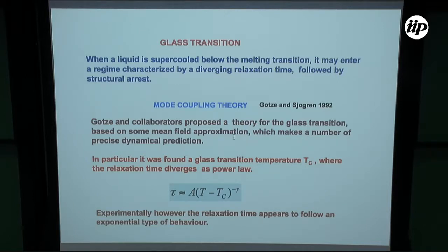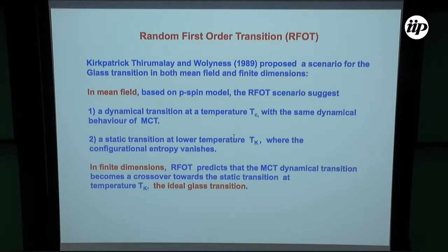So tau goes as T minus Tc to the minus gamma. And as you know, experimentally, the relaxation time appears to follow a different type of law, mainly an exponential type of law. At the same time, Kirkpatrick, Thirumalai, and Wolynes proposed a different scenario. No, not different, but a more complex scenario, which goes by the name of random first-order transition.